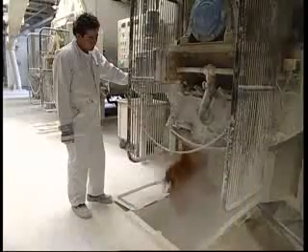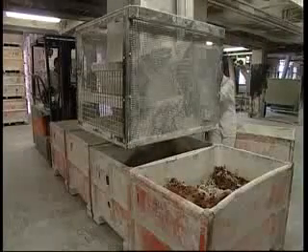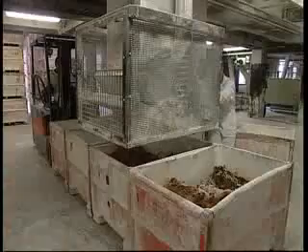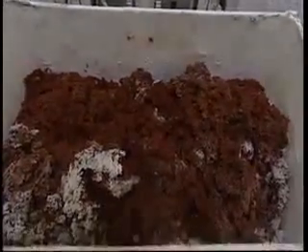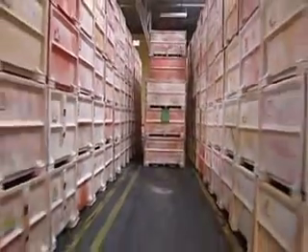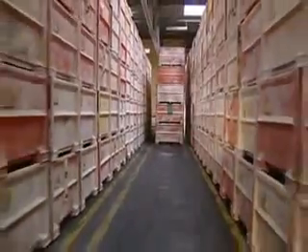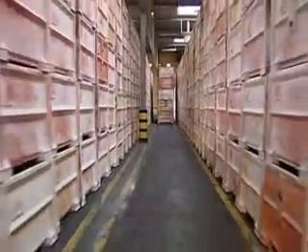It's a tough, compact substance which is poured into containers from the mixing vats in measured amounts. The white chalk which you see ensures the linoleum cement does not stick to everything. After the rosin and linseed oil has been mixed, the linoleum cement requires time to achieve the correct composition. It's stored for the second oxidization process. In this storage area, the ripening process of the linoleum cement continues for about a week before the raw material reaches the correct quality.